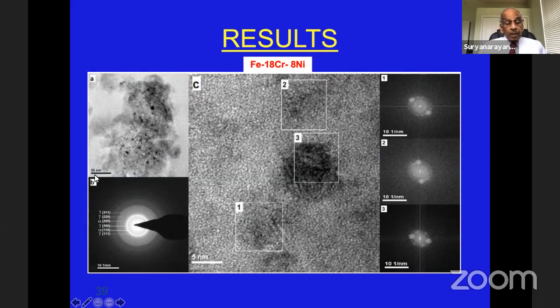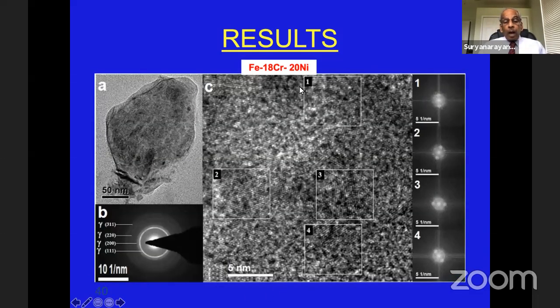You look at the grain size. This is 50 nanometers. This is obviously less than about 10 nanometers. And when you go to a higher resolution, you can find out what the actual diffraction patterns are in different regions. And what you would notice is the presence of both alpha and gamma, that means ferrite and austenite. And the same thing is in this particular case, in just one general area. But if you can choose any one particular area and use this microbeam electron diffraction or nanobeam electron diffraction, you'll be able to get a better picture. On the other hand, you go to 20% nickel, everywhere you will see only austenite. That means the X-ray diffraction results are confirmed using this particular type of technique also.